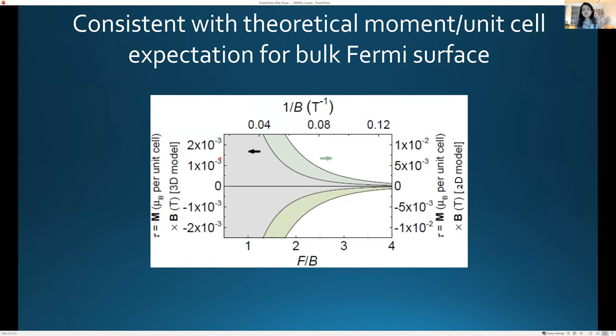It's also the case that other groups have measured the mobility of the surface, which is very, very poor. So it's unsurprising to some degree that we didn't see resistive oscillations. It's probably because the surface has very poor mobility, which also would make it very strange if we got prominent quantum oscillations from a disordered surface.